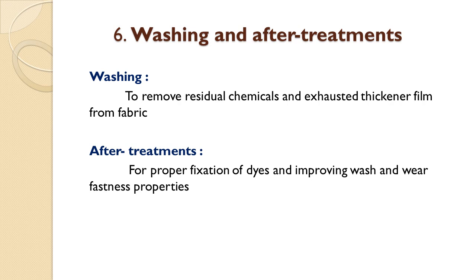So the after treatment in case of vat printing is proper printing with alkaline reducing paste, drying, then steaming, followed by after treatment with acidic oxidizing condition, then it can be washed and soaping can be done.